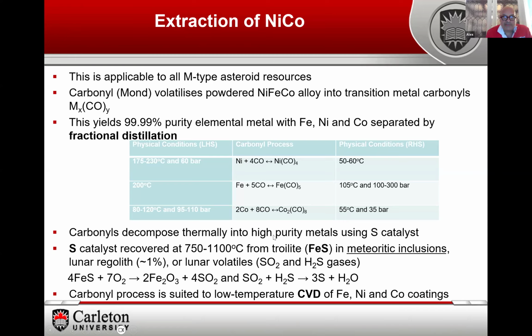We do need a catalyst for this, sulfur, but we can recover sulfur from troilite. Troilite, fortunately, occurs in meteoritic inclusions that we get with M-type asteroid material, so it's already there with the metal, and so we can extract this quite readily to end up with sulfur.